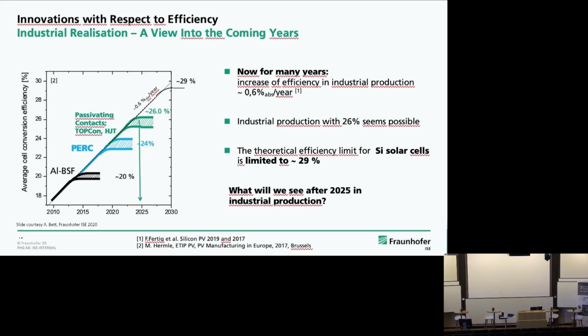Heterojunction technology, completely different approach. You cover both sides of the wafer with amorphous silicon. On one side, P-type amorphous silicon, on the other side, N-type amorphous silicon. And then you have amorphous silicon in contact with crystalline silicon, which is a perfect passivation for the silicon because it's only silicon-silicon bonds. But in addition, today we know how to dope amorphous silicon, so you can as well use this amorphous silicon as a good contact to the silicon. So heterojunction technology is an alternative to TOPCon.